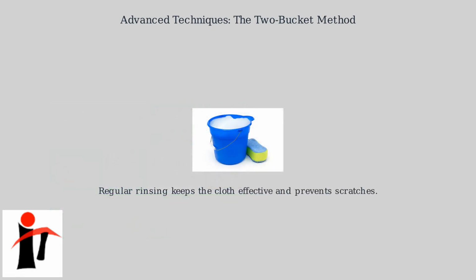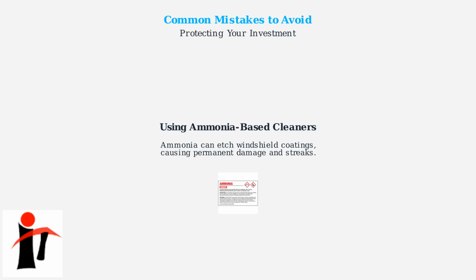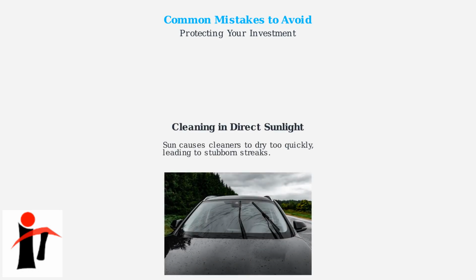Regularly rinsing your cleaning cloth in the dedicated rinse bucket is crucial. This removes accumulated dirt, maintaining the cloth's effectiveness and protecting your windshield from potential microabrasions that could damage the glass coatings. One common mistake is using ammonia-based cleaners. Ammonia can etch the windshield's specialized coatings, causing permanent damage and reducing their effectiveness against rain and debris. Another pitfall is cleaning in direct sunlight. The heat causes cleaning solutions to evaporate too quickly, leaving behind streaks and residue that are hard to remove.